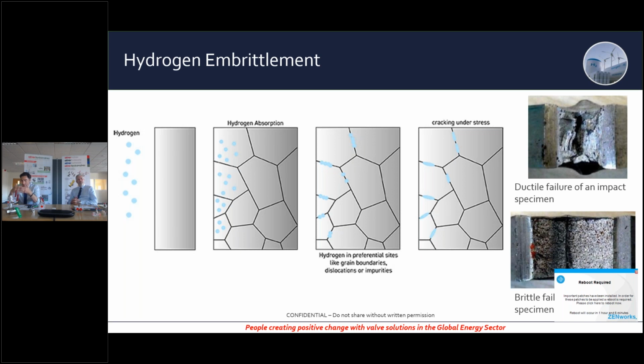Now, to have hydrogen embrittlement, you effectively need three things. You need the presence of hydrogen, which obviously for this discussion is pretty obvious. We need a stress or a load, which again, for a pressure retaining component such as a valve is going to be inevitable. But you also need a material that's susceptible. So take one of those points away and you can safely move away from hydrogen embrittlement. So our approach is to use a material that's not susceptible. So we've standardized our range on austenitic or super austenitic stainless steels, such as 316, widely used in the industry, but well known in metallurgical terms to be not susceptible to hydrogen embrittlement in most cases, which we'll talk about later.